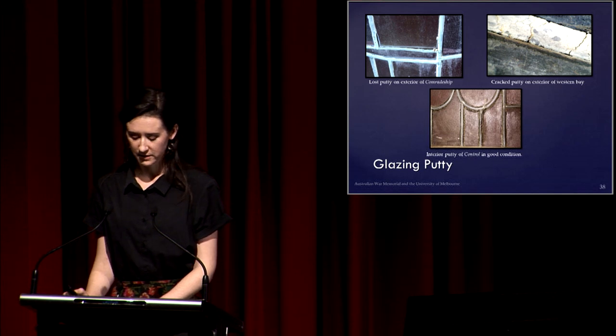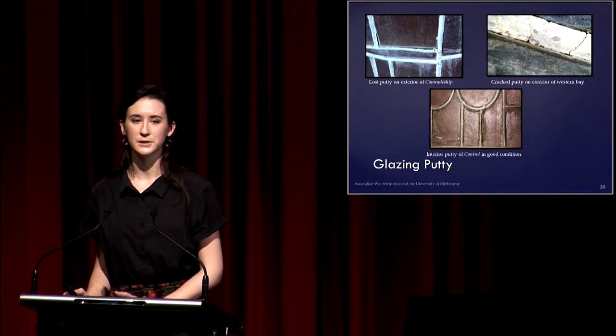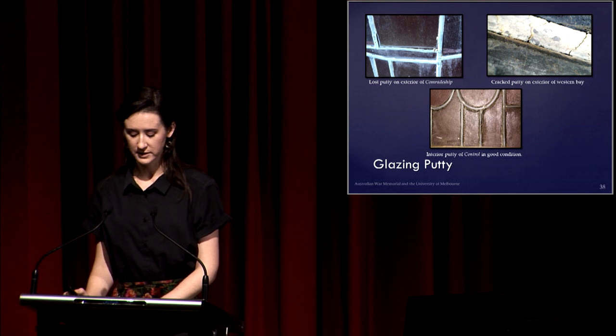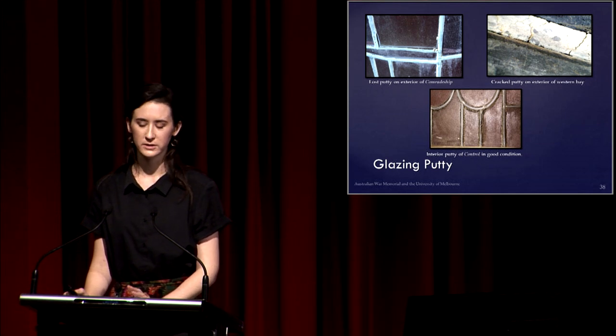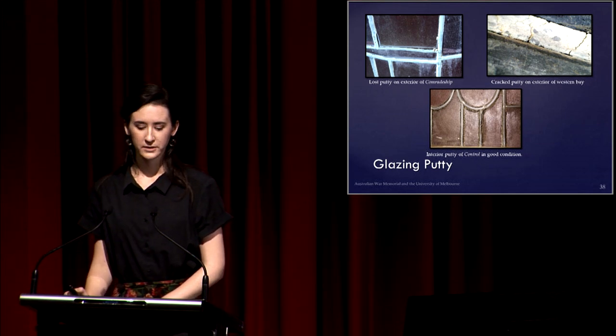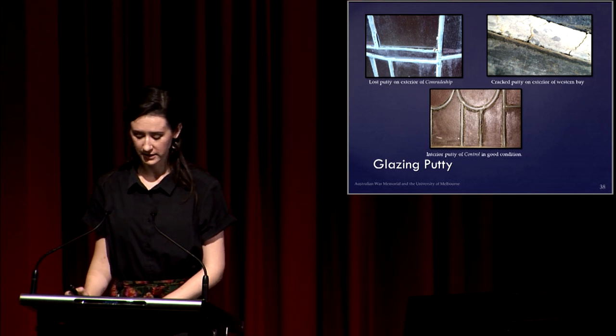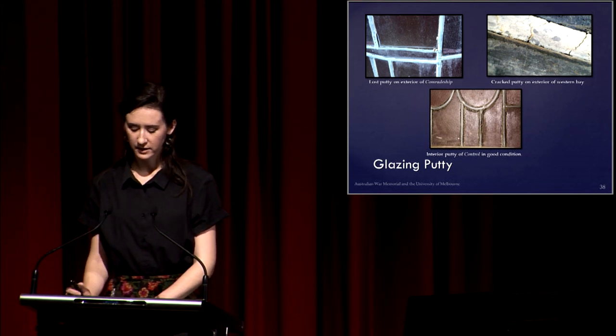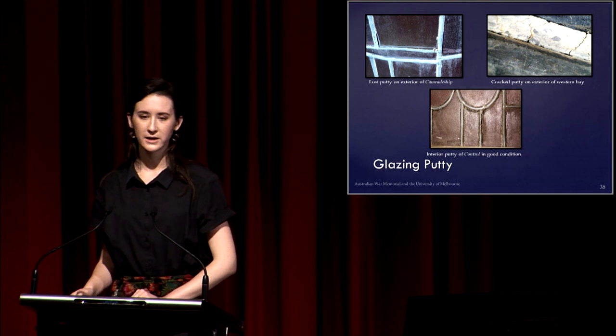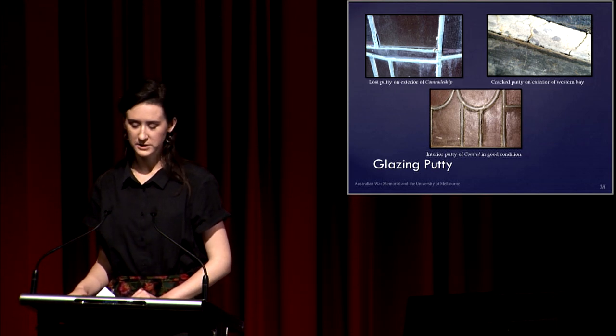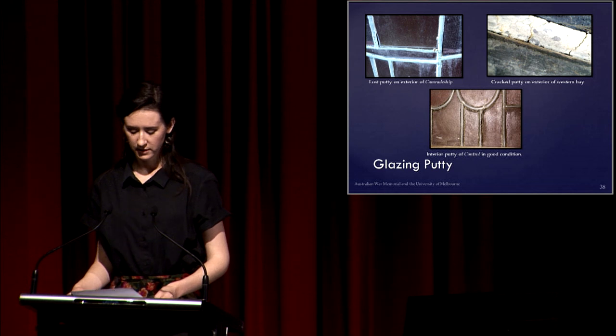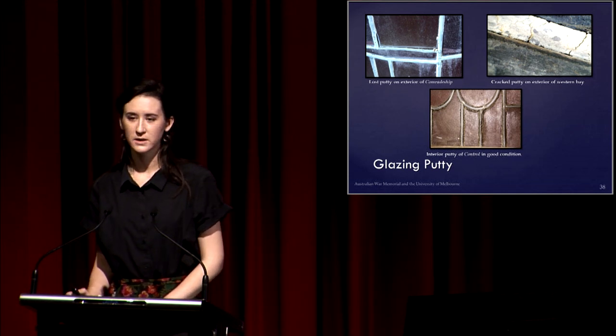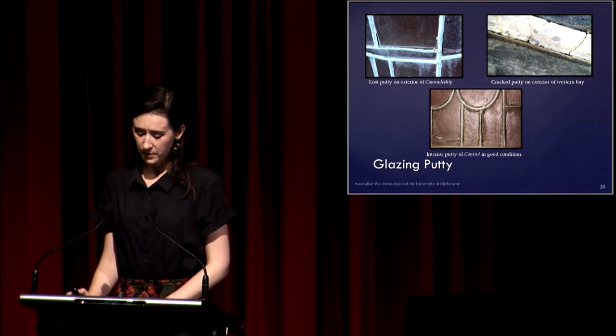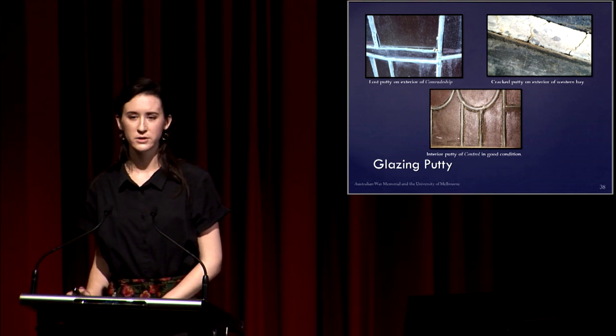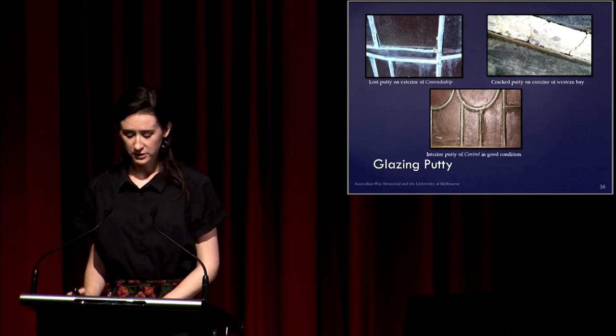The glazing putty between the glass and the lead plays a really big role in stabilising the whole matrix and is often overlooked in its significance. The linseed oil used in the glazing putty is damaged by light and water exposure, which causes cracking, powdering and loss, particularly on the exterior face. This leaves voids for ingress of water, pollutants and biological growth that can cause corrosion of the leads, water damage to the glass, and further putty loss.